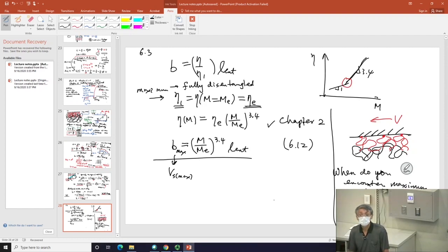Before that, you have a whole spectrum of partially disentangled interface. Consequently, just by this formula, you have B ranging from nearly 0. The minimum value is, of course, this, which is very small. For our melt, we're talking about 5 nanometers here.